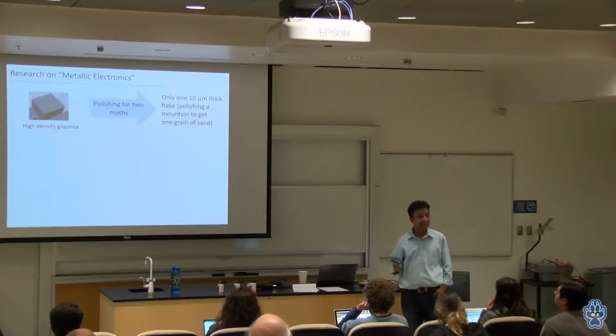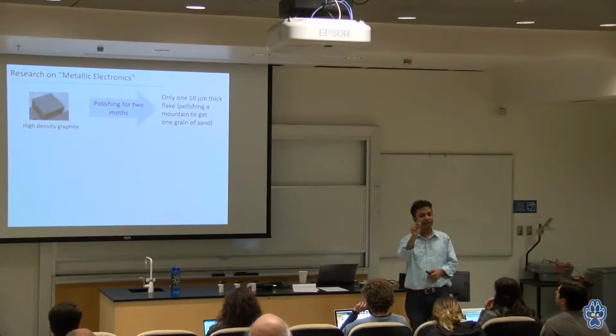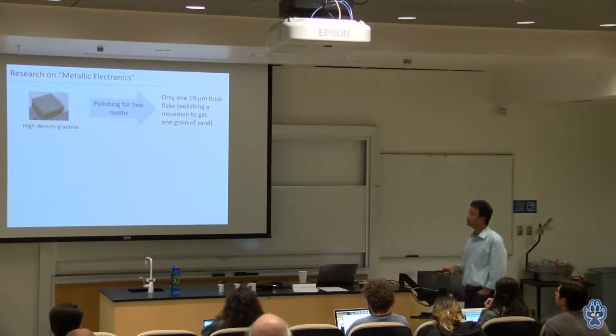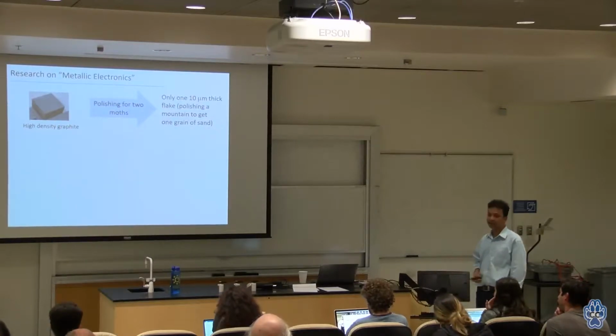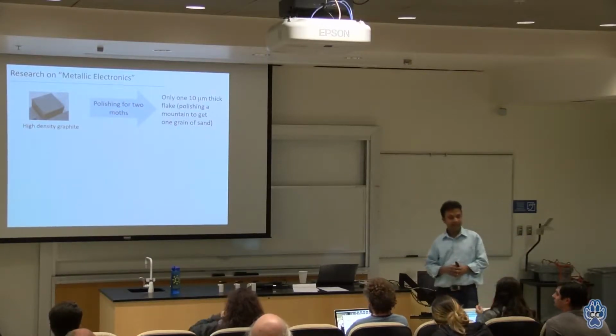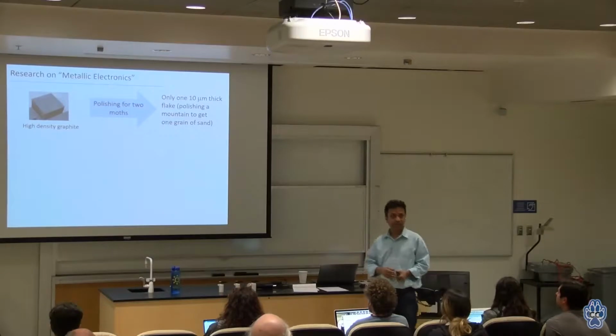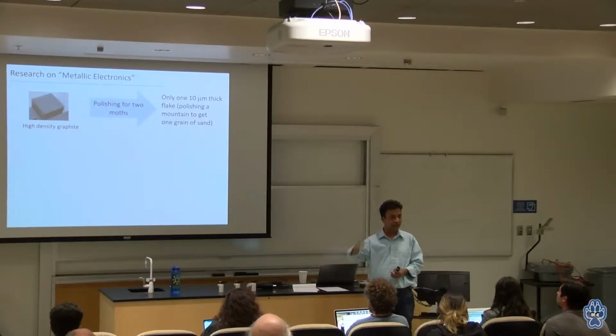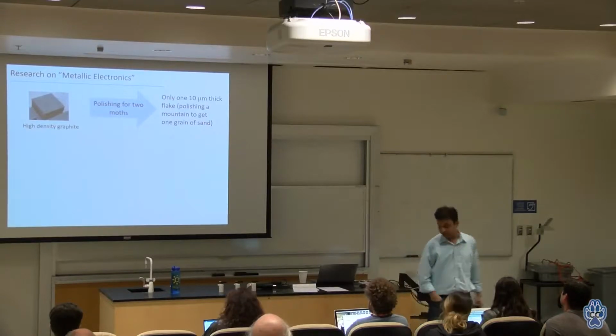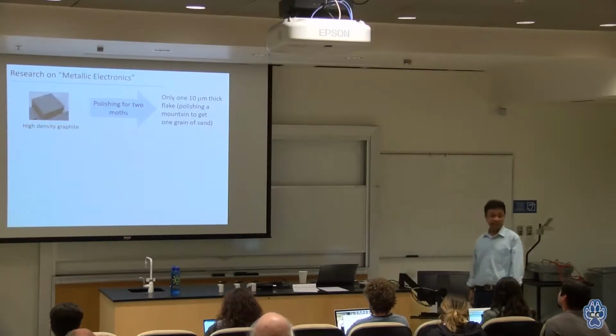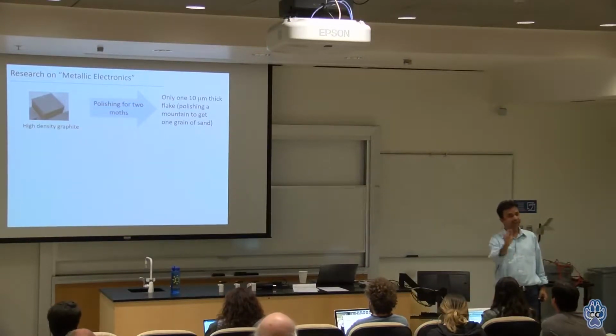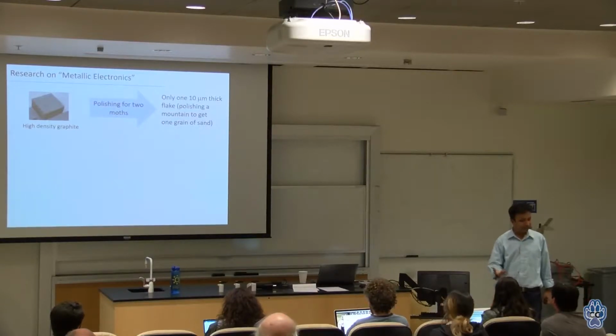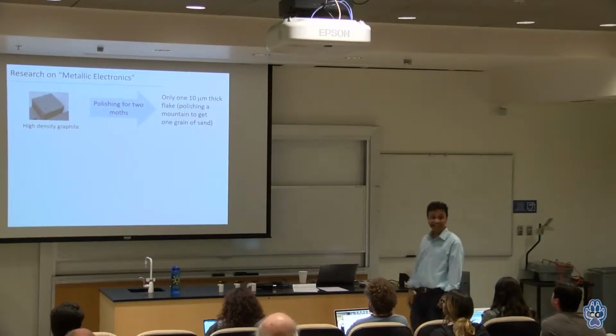But his idea was, if you have a very, very thin metal, maybe you will be able to get it. So what he did is use high density graphite, and he gave it to the student. This is the graphite, and we know it's a layered material. Try to polish it as thin as possible. So the student spent 2 months polishing it and got one flake of graphite. This is the thinnest one.